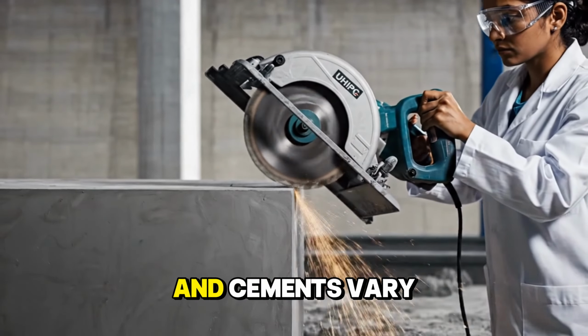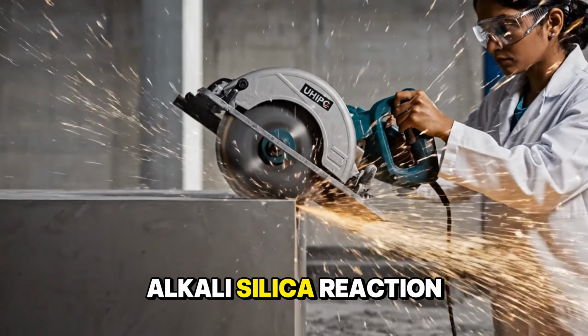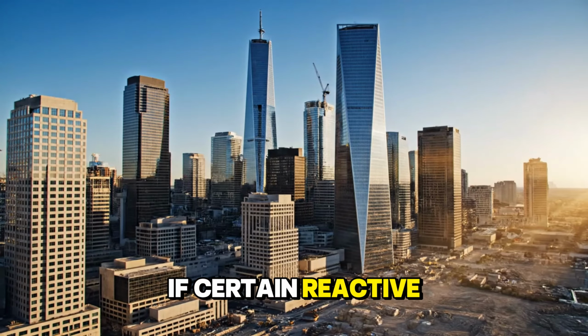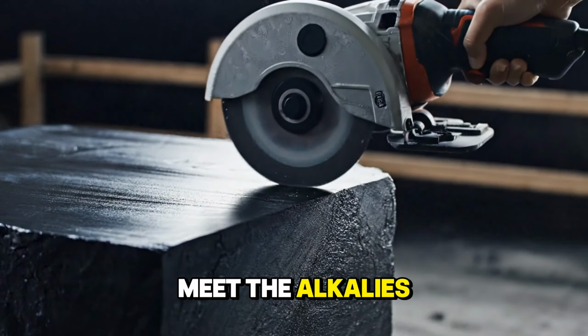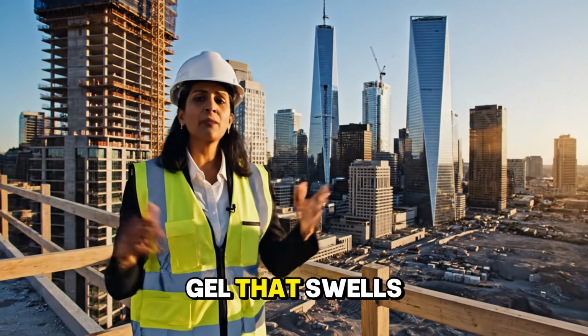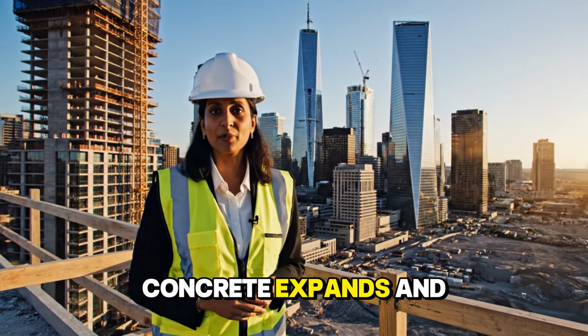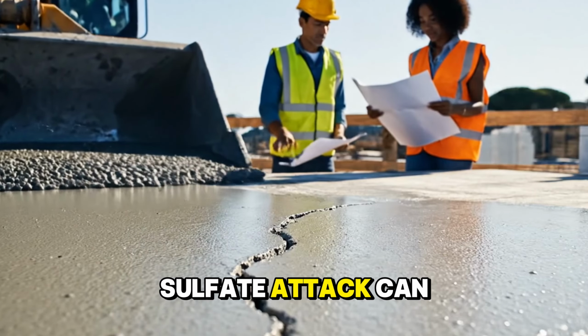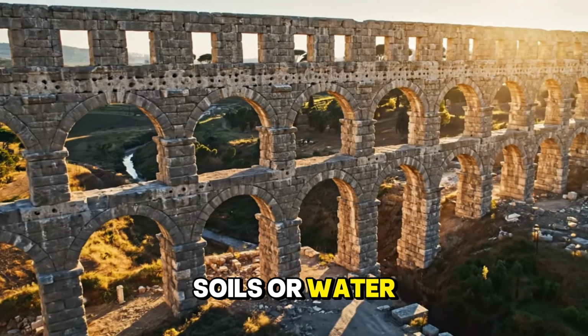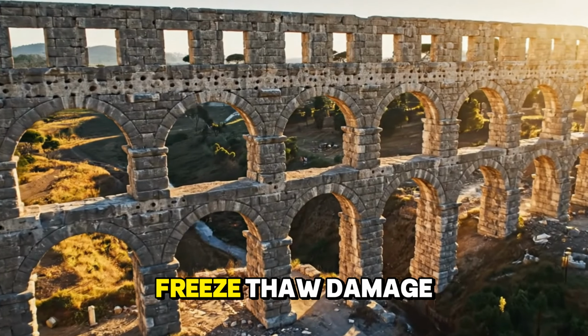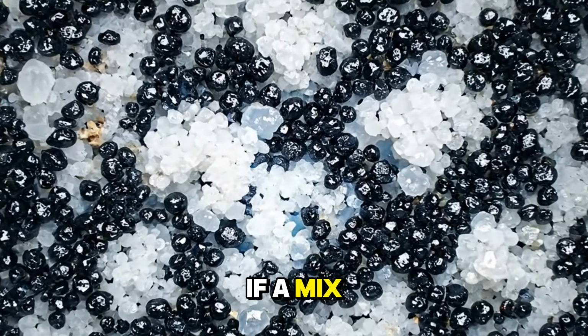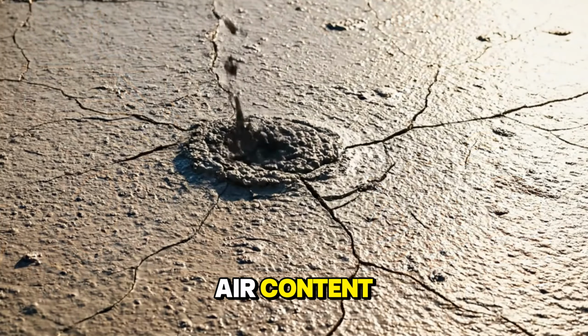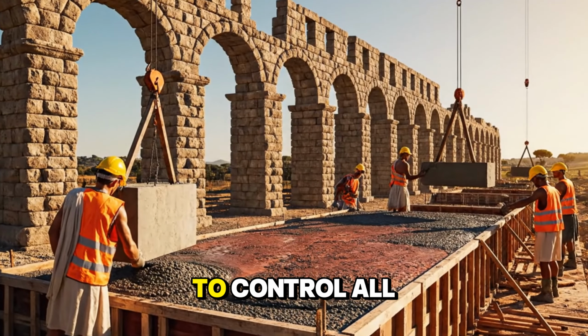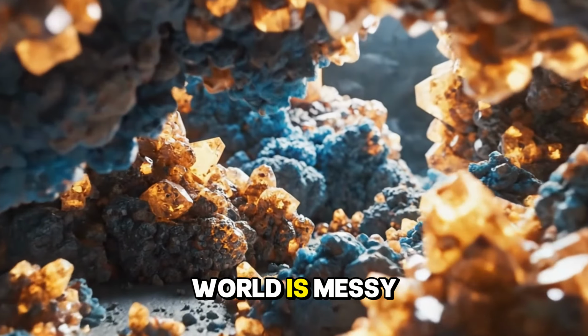Fourth, our aggregates and cements vary. Alkali-silica reaction can pop up if certain reactive sands or gravels meet the alkalis in cement. It forms a gel that swells when wet. The concrete expands and cracks. Sulfate attack can hit when ground soils or water carry the wrong chemistry. Freeze-thaw damage can shred pores if a mix was not designed with the right air content. Modern standards try to control all of this, but the real world is messy.